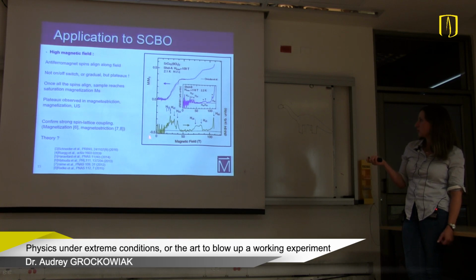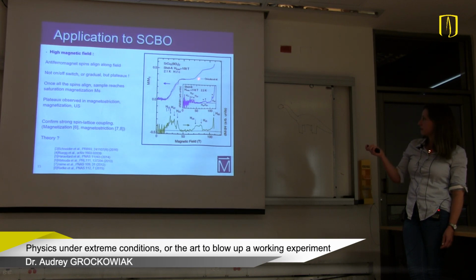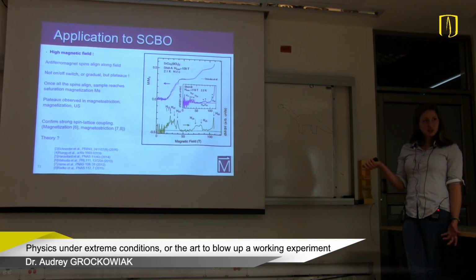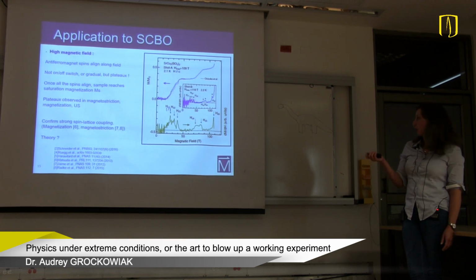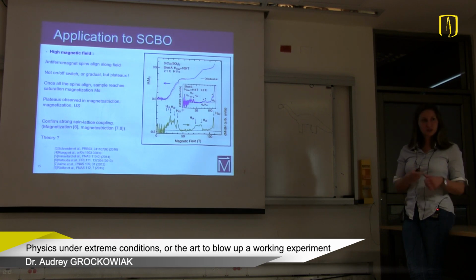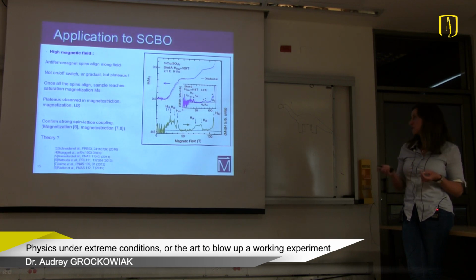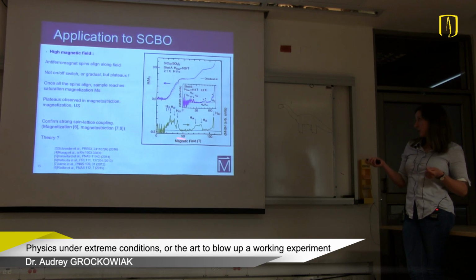And you can see it here on this plot. So the magnetization as a function of magnetic field, and you're looking at this curve here where you see steps appear in the magnetization. It doesn't look like much, but first, there is no theory behind that. That was not predicted, so nobody really understands the mechanism. There are several propositions, but nobody really understands why those steps appear and why they are integer fractions of the full magnetization.